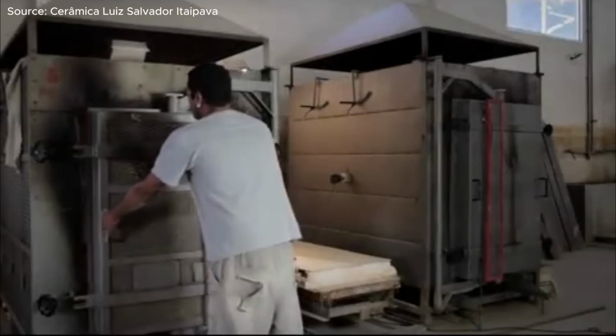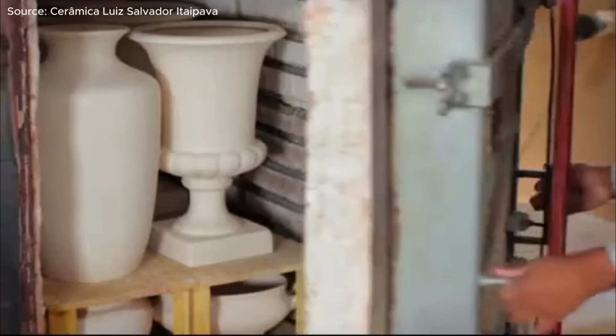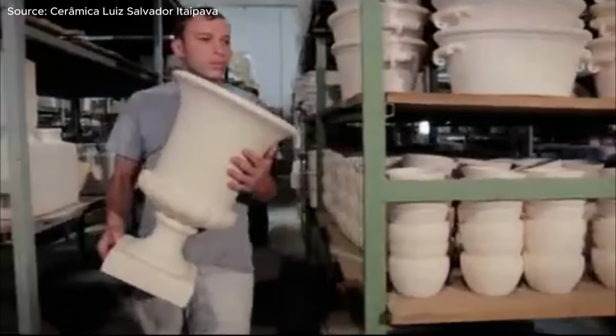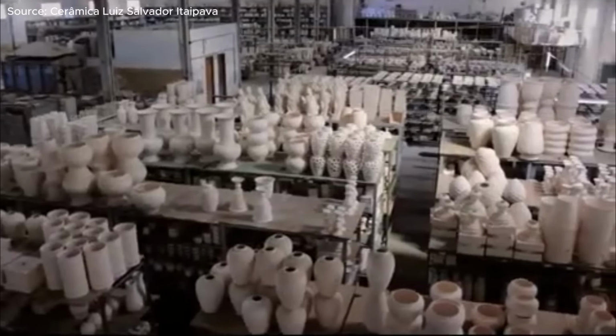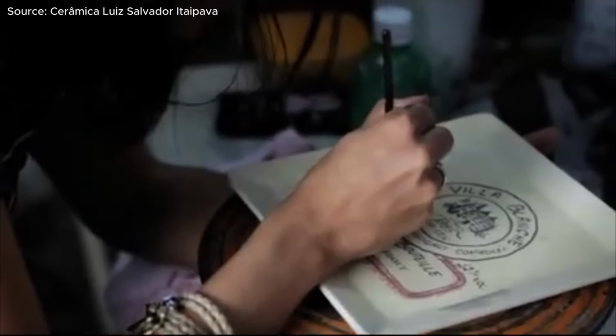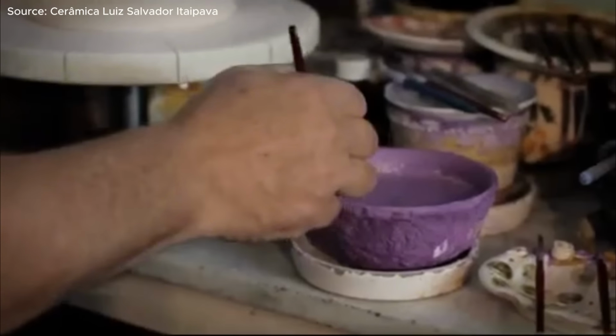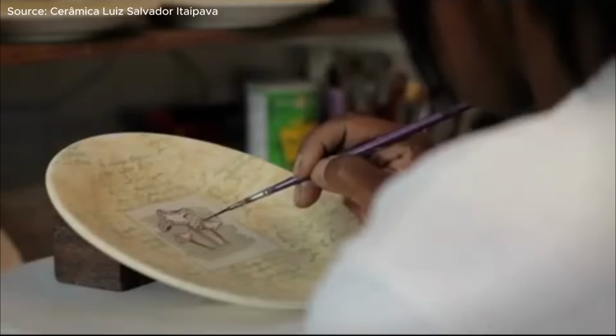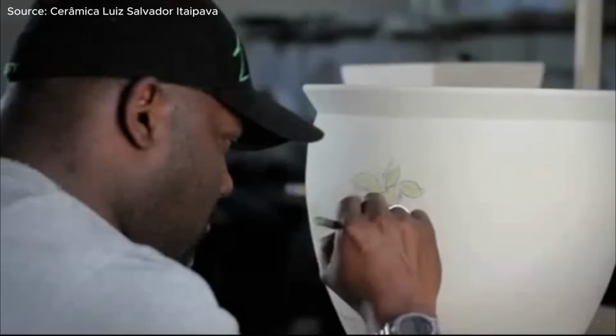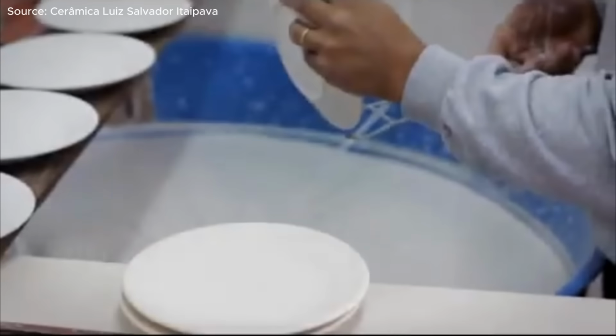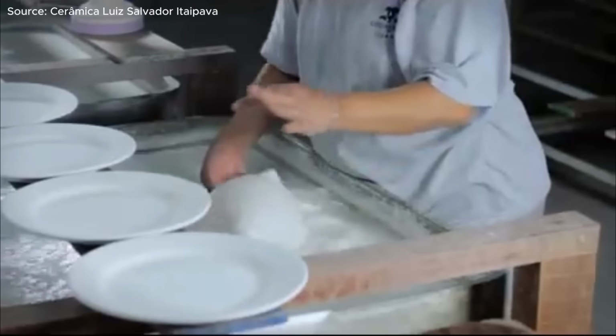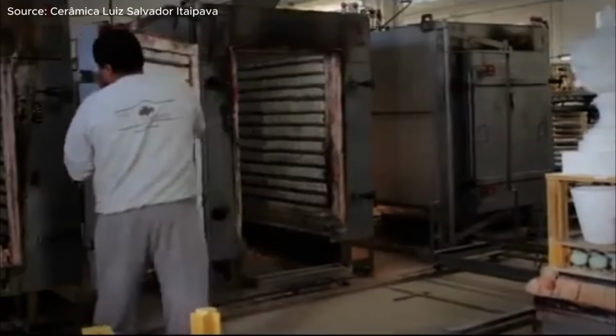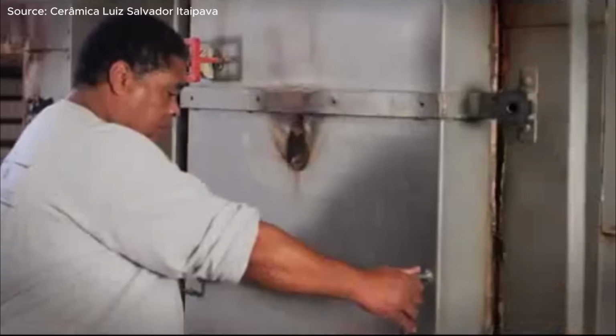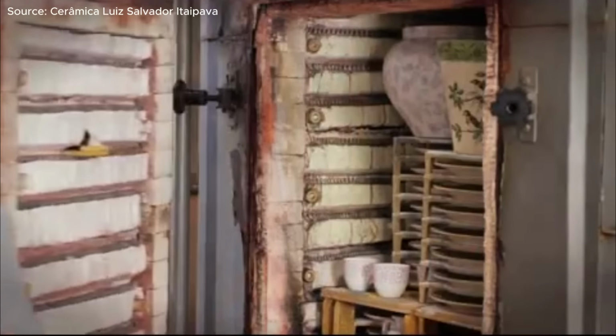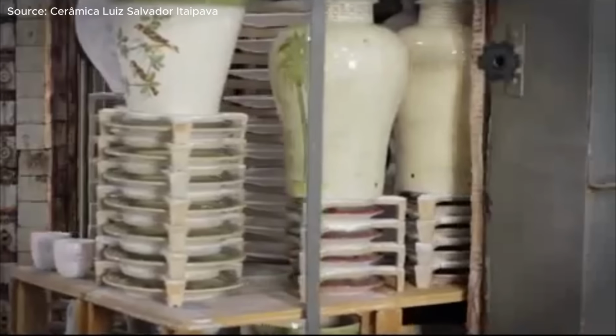The first firing, carried out in kilns at temperatures up to 1050 degrees C, transforms the material into biscuit, durable, and ready for subsequent stages. Each item is then hand-painted with carefully developed pigments before being coated with opaque, colored, or transparent glaze. A second high-temperature firing vitrifies the surface, bringing durability, brilliance, and the unmistakable shine of Luís Salvador Ceramics.